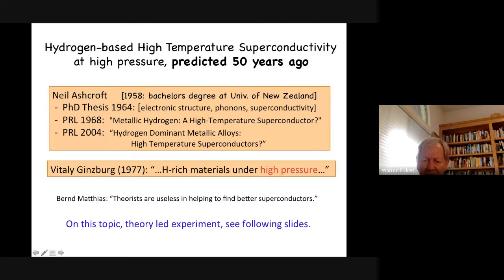The theory wasn't well enough developed, in both the electronic structure and the amount of pressure, so he didn't offer a number for how high the temperature might be. He didn't know; the information wasn't available. And metallic hydrogen doesn't yet exist, at least there's no consensus. There have been 3-4 published papers claiming to see signals of metallic hydrogen at pressures of more than 300 gigapascal, more than 3 million atmospheres, and the best calculations suggest that hydrogen will become elemental, not molecular, and metallic around 500 gigapascals.